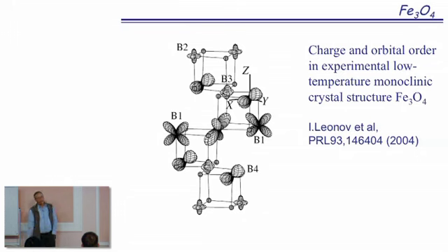Now that is the result. As soon as we applied the correction, immediately we got beautiful charge and orbital order. I should say explicitly here that formally it is orbital order, and that means that the difference in D occupancy should be 1. It is not 1. It is something like 0.1, 10 times smaller.